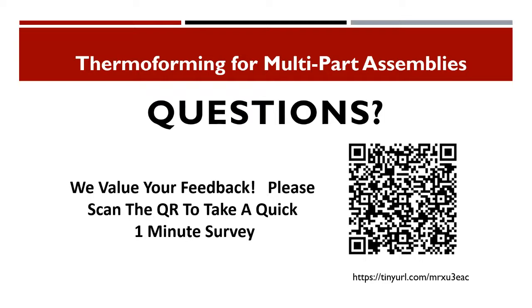Thanks for that. So is the mold itself heated or cooled, or is just the material general? Let me clarify this in a couple of different ways. I'm not saying you cannot form parts on wood molds and composite molds, because we do it every day. But in order to achieve the best parts with the highest quality, we need temperature-controlled aluminum molds. These molds are controlled with temperature, generally with water that is connected to a thermolator.